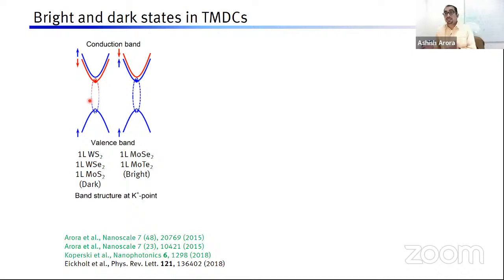Now, if the low energy state in a crystal is dark, that means it will not be a good emitter of light, because the emission comes from low energy states, right? So it's very important to understand if there are low energy dark states inside a material or not. For MoSe2 and MoTe2, what's found is that the lower energy conduction band has the same spin as the top of the valence band, and then you create a bright exciton. So the lowest energy state in MoSe2 and MoTe2 is bright.